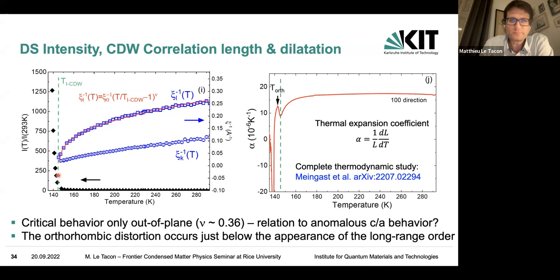Now, if we look at what's going on in the thermal expansion, you see that the temperature at which the intensity strongly increases corresponds to the downturn of the thermal expansion, which is just preceding the orthorhombic distortion. So in other words, it looks to me like the long-range CDW order forms, and just below, the system exhibits the orthorhombic distortion.